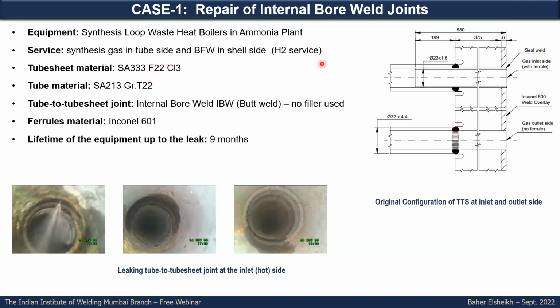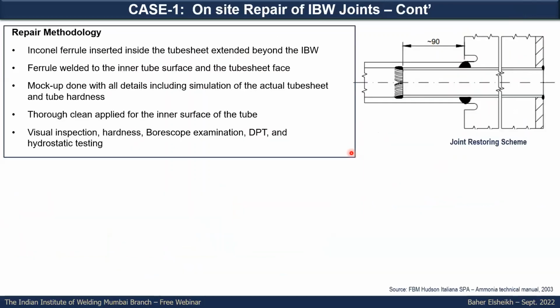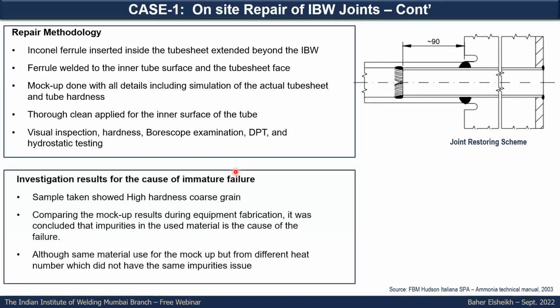The service is in hydrogen service, and there is a weld overlay here, with welding between the tube and the tube sheet, as you can see in this configuration. This one was repaired at site, where they installed a ferrule inside the tube and welded it to the tube inner surface from here and the tube sheet surface from the outer side. They made many mock-ups until they had good confidence in the applied technique.